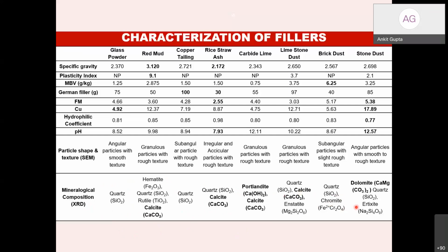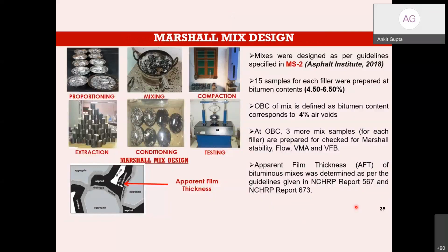A higher amount of silica content will lead to failure in the moisture, because if silica is there on the surface of an aggregate, then the bitumen cannot have a strong bond with the silica. There will be a repelling action, and in the presence of moisture, the bitumen loses contact with the surface of the aggregate. And that has been seen in the results also.